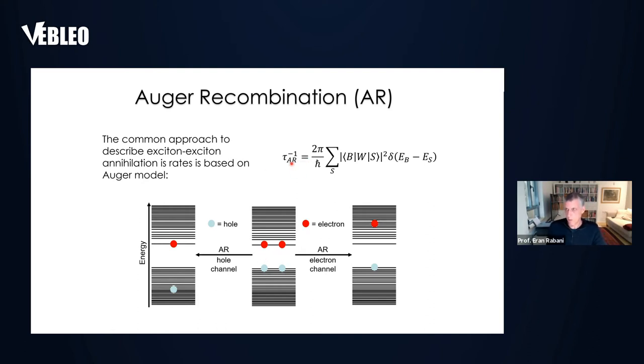This process immediately tells you that you've lost one quantum of excitation, and that reflects itself on the quantum yield. Mathematically, the way we calculate these processes — assuming it's a rate process — is using Fermi's golden rule. Fermi's golden rule is very simple: you sum over all final excitonic states S, starting from an initial biexcitonic state, and you conserve the energy of the initial and final states. The energy of the biexciton and the energy of the single exciton has to be conserved.